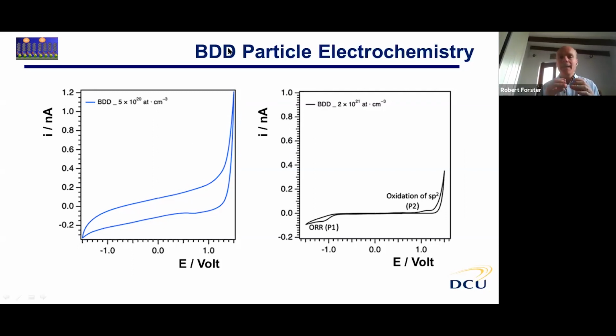But remember that in a bipolar experiment, one end of the electrode is oxidizing, one end is reducing. And just like any electrochemical cell, if the oxidation and reduction are not balanced, the slow step will dictate overall performance. So we need a reduction reaction, and ideally that's oxygen reduction. At low boron doping, the oxygen reduction reaction is quite poor, but it's much better at higher doping, giving much better defined oxygen reduction. That's important because we don't want the ORR to limit production of hydroxyl radicals.